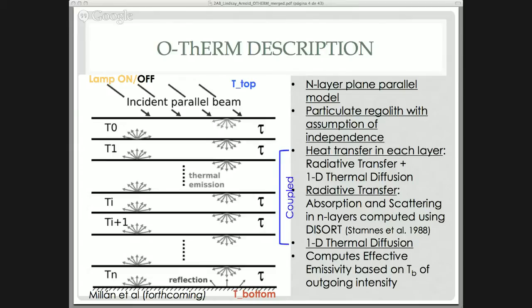What it does is calculate the radiative transfer and the 1D thermal heat diffusion to figure out how we're going to be updating and changing the temperature gradient over time. We fix a temperature at the bottom and the temperature at the top. We can have illumination from the top by simulating either a lamp on or a lamp off. Basically, DISORT will track the scattering environment through here. Eventually, we'll use that to update and find a temperature gradient, which will then give us the emissivity that's leaving the regolith surface. That's a sort of quick workflow, and now to introduce some of the inputs that we have.